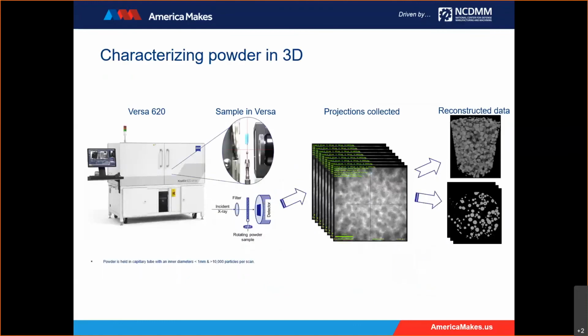So the final technique that I want to talk about today is X-ray microscopy. If you have a micro CT, you can use it to look at your AM powder. We use a Versa 620, and we place a powder sample in a capillary tube between the source and the detector, and rotate the sample to collect different projections of the sample. And then we can reconstruct the data into a 3D volume.